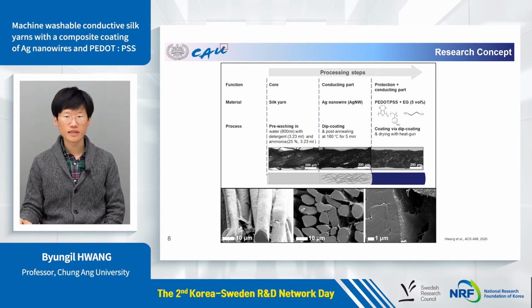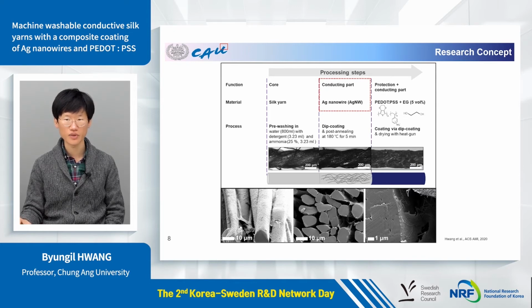As briefly explained in the previous slide, the concept of this research was to insert silver nanowires between the core silk filament and the PEDOT:PSS coating. For this, the pre-washed silk yarns were dip coated with silver nanowires, followed by post-annealing at 180 degrees C for 5 minutes. As a final step, the silver nanowire-coated silk yarn was coated with PEDOT:PSS, followed by drying using a heat gun. As can be seen in the scanning electron microscope image below, the overall silk yarn surface was covered with silver nanowires, and PEDOT:PSS also covered the silver nanowires and silk surfaces.